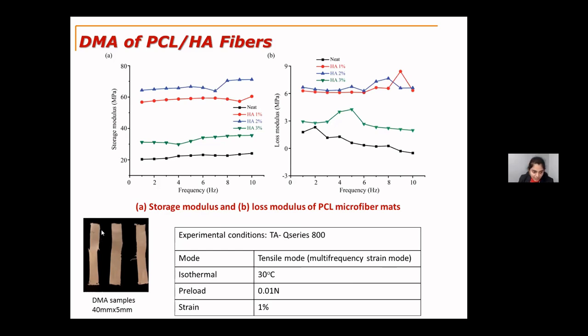And these are the tested samples. The samples are cut into 40 by 5 mm. I measured the width and thickness of these fibers at 10 different points and averaged the thickness of these samples. The preload applied on these samples is 0.01 newtons, which is consistent with the tensile test. And a constant strain of 1% is applied before doing this frequency sweep method.